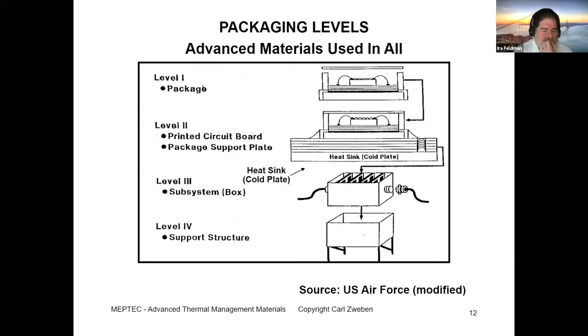So Carl, just a quick question. Is the ideal case always to have a CTE match of what you're mating, or are there cases where you want the heat spreader to be a lower CTE than what you're connecting it to? Well, generally you're trying to match the CTE of various components. Although for an optical system where you're concerned about deformation, what you want is a material perhaps with zero coefficient of expansion, so there's no deformation at all. And I'll show you an example of that later on. Thank you.